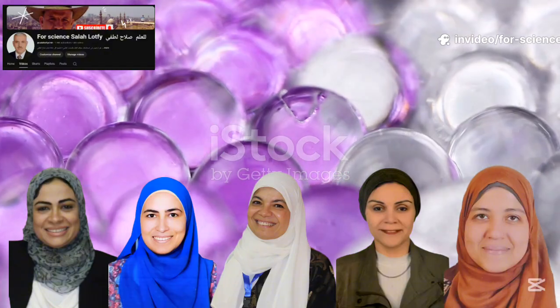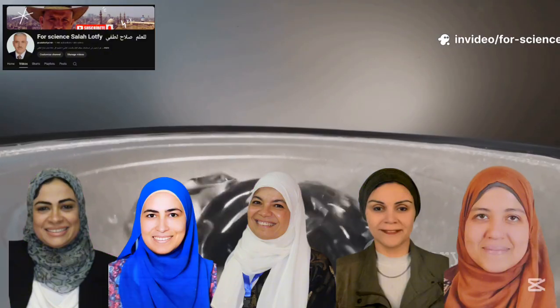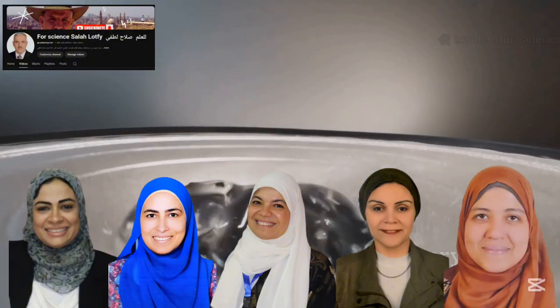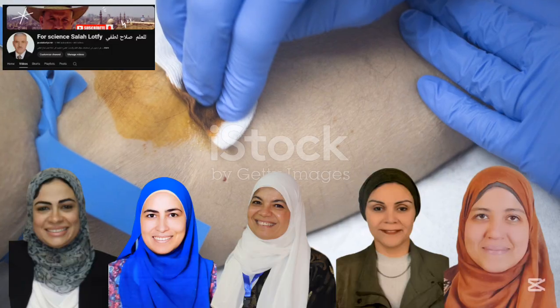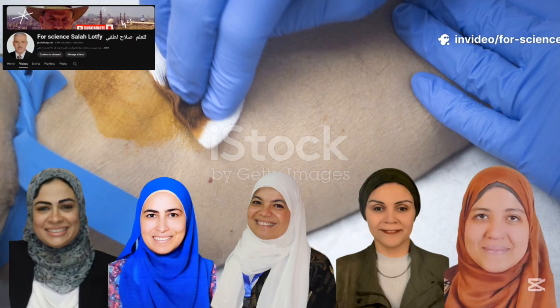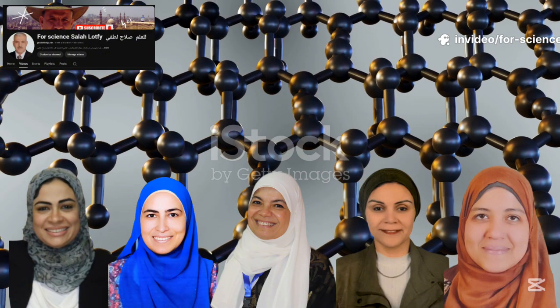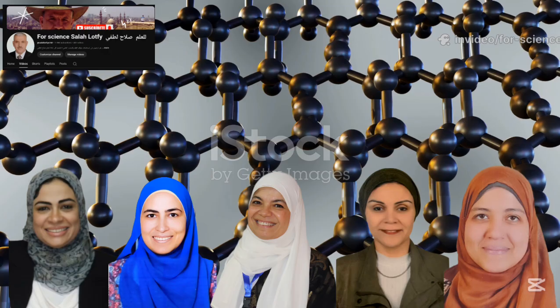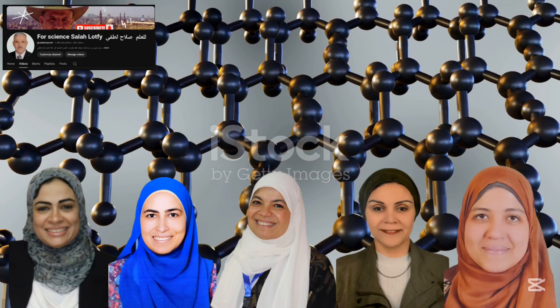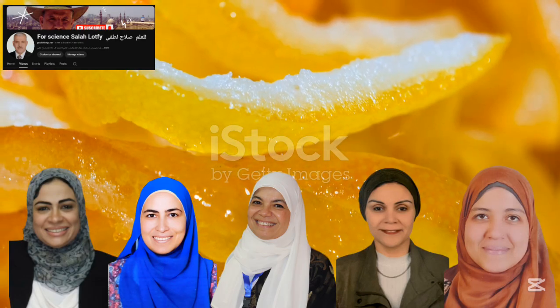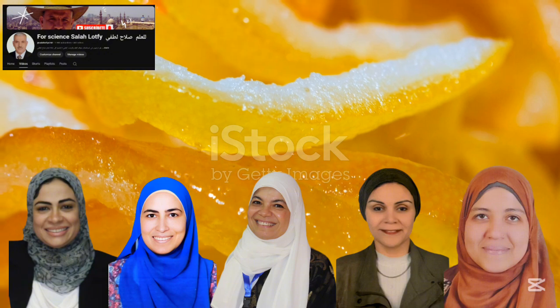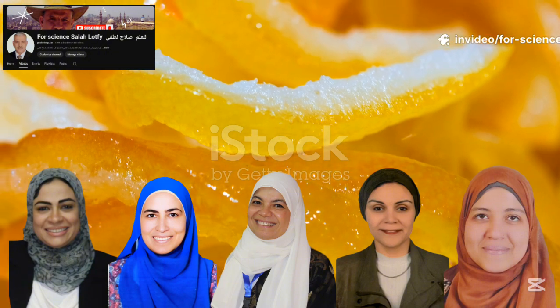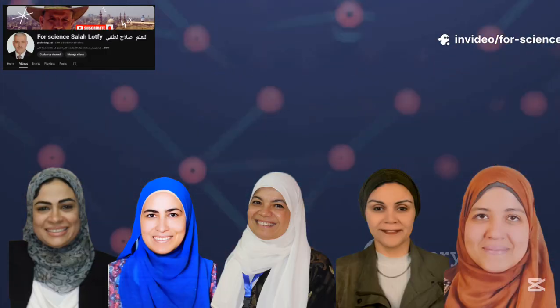This is where hydrogel technology comes in. Hydrogels are 3-dimensional polymer networks that absorb fluids, keep wounds moist, and allow oxygen flow. They do not stick to the wound, making dressing changes painless. In this study, researchers combined polyvinyl alcohol, PVA, a synthetic non-toxic polymer with strong swelling and mechanical stability, with pectin, a natural polymer from citrus peels, known for its biocompatibility and anti-inflammatory properties. Together, they form a hybrid hydrogel dressing with improved performance.